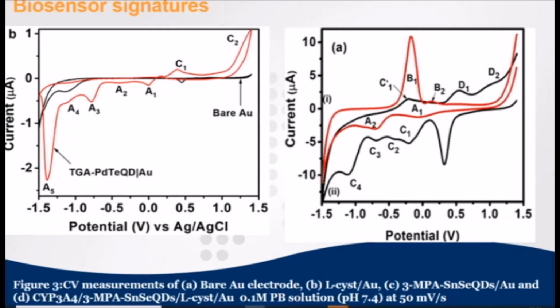One is after the binding. The second one is after the addition of the oxygen. So in this case, we are looking at the 2 reduction peaks. We have a reduction peak around minus 0.1, and another one at minus 0.6. These are the signatures for the heme center, because we are moving the state from iron 3 plus to iron 2 plus. So this is what is happening after changing the states.